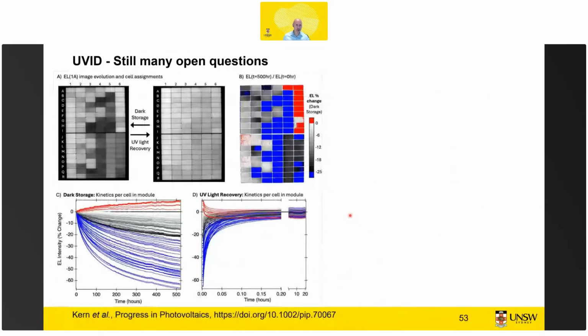So this is great work by NREL, where they looked at, in this case, the dark storage kinetics per cell, and it's just all over the place. That's a bit strange because these cells, of course, are from the same production lines. They're binned to be roughly identical. They would also likely be produced quite closely together in time. But you see their UV extent is very different, which is still something we don't understand.